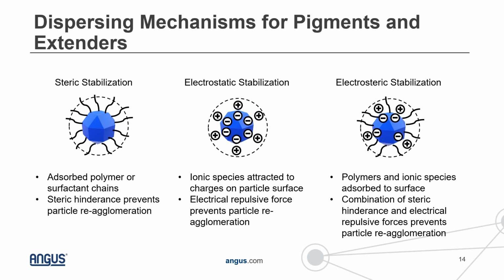The third category is essentially just a combination of the first two. This is electrosteric stabilization, and this is the reality of most coating formulations, where it's not just one or the other. You usually have a combination of polymers, surfactants, or ionic species adsorbed to the surface of the pigment particles, that together prevent the reagglomeration of those particles.